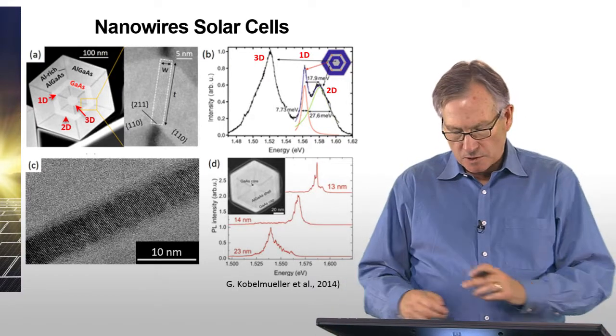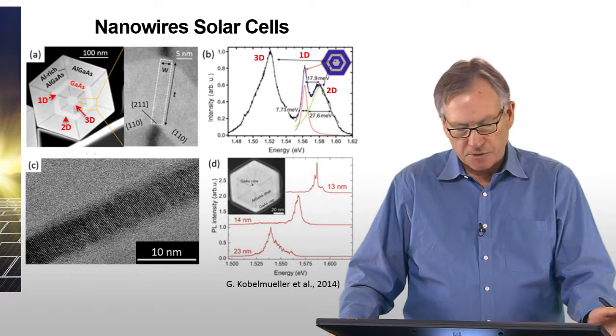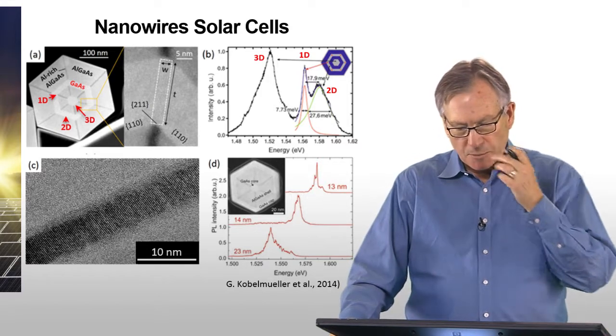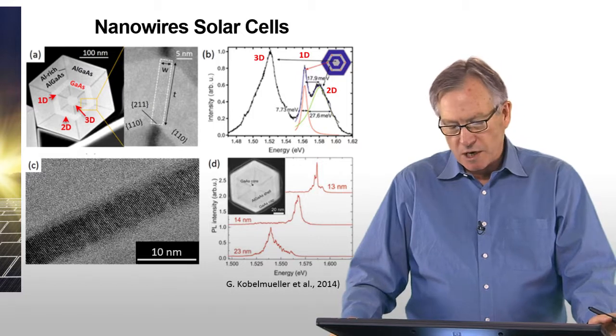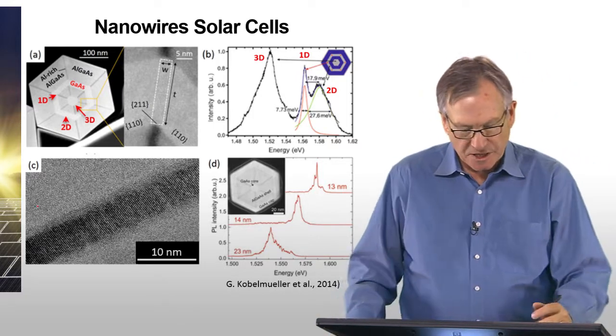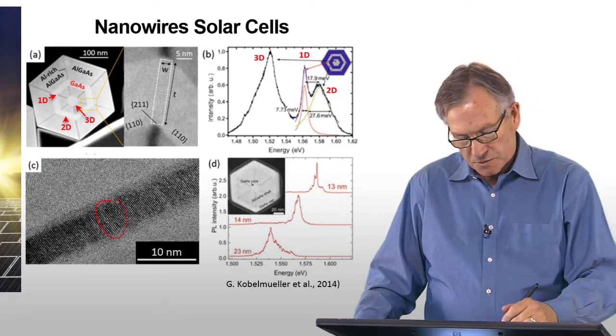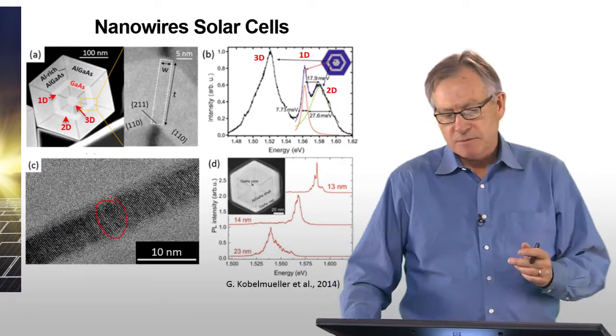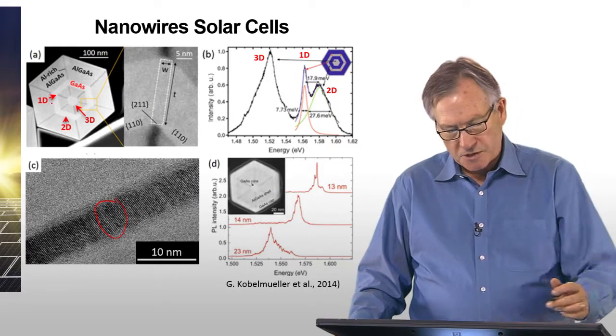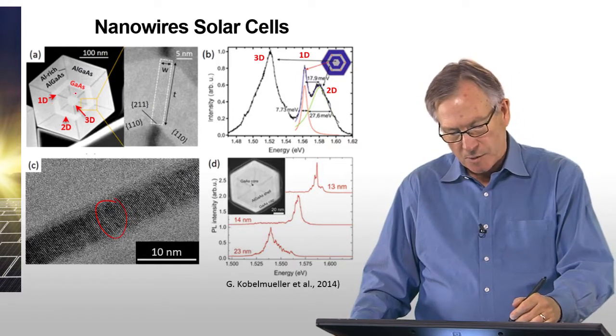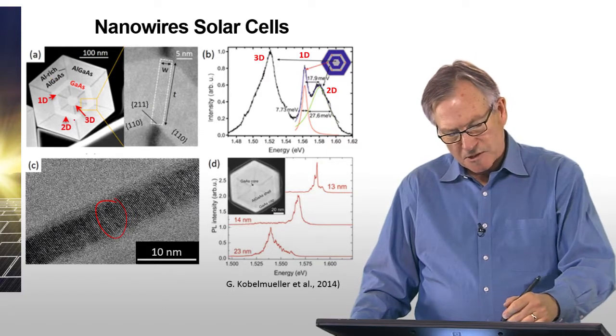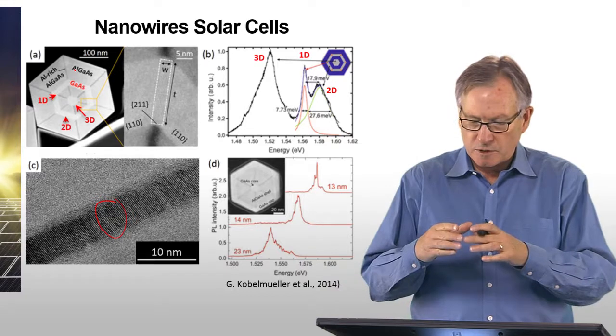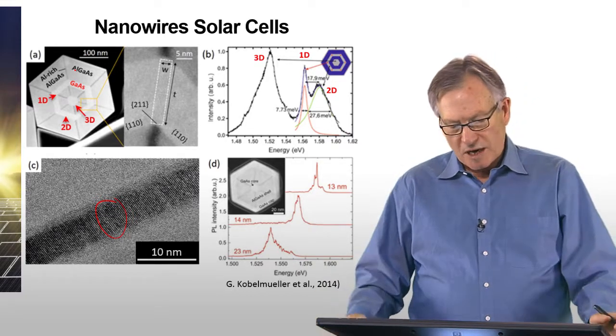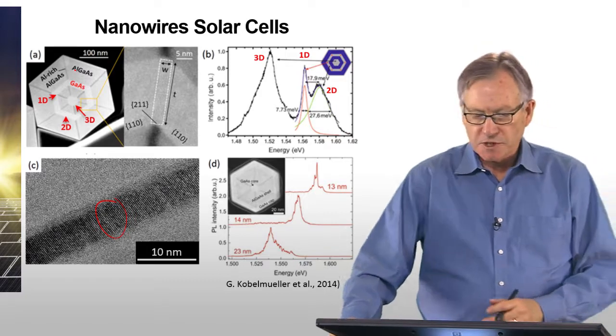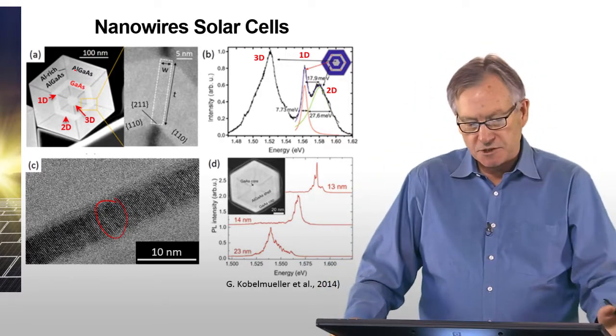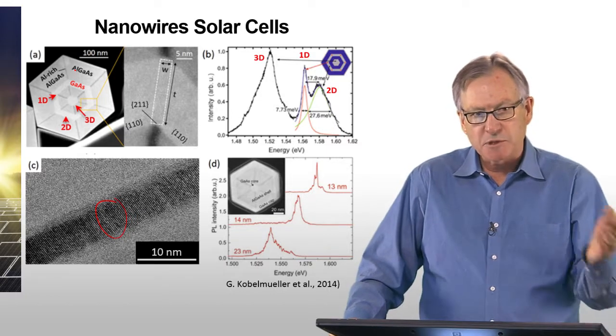Another approach, which is going on at the Technical University of Munich and which we've been collaborating with in terms of modeling, is to use nanowires. This is a picture of a self-assembled nanowire. Again, it's a microscope picture which shows the crystalline structure of the nanowire. And this is a cross-sectional view of a nanowire in which a gallium arsenide nanowire has been grown, and then aluminum gallium arsenide has been grown around it to make a heterojunction, what we call a coaxial heterojunction nanowire. These are of great interest right now for optical applications, for making high mobility transistors.